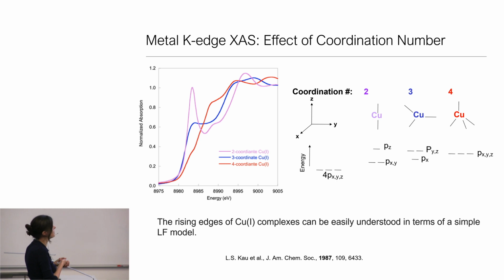Now, if we go to a 3-coordinate complex where I have 3 ligands within the YZ plane, then both Y and Z will be raised due to those antibonding interactions, and I predict that I should have a single PX transition with roughly half the intensity of the 2-coordinate that had a doubly degenerate PXY, and that's also what I see. Then when I go to a 4-coordinate copper 1 that's tetrahedral, I'm going to raise the energy of the PX, PY, and PZ symmetrically relative to either the 2 or the 3-coordinate complexes such that I expect the degenerate XYZ to largely be buried in an edge transition. And that's also roughly what we see in the red spectrum.